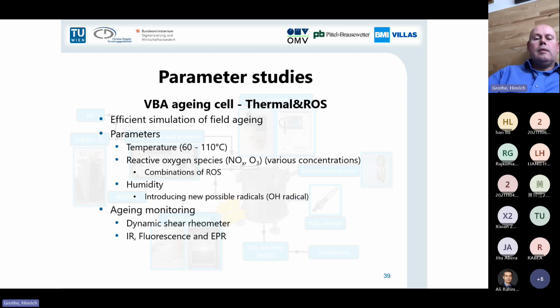So we were performing studies on the aging, and we were not using the pressure aging vessel test, but we were developing our own system. It's a Vienna binder aging. And the difference really is that here we can apply reactive oxygen species. That means we are using nitrogen oxide, we are using ozone, we can even apply light, form OH radicals if we want, and we can change temperature. We can control and analyze the gas phase very sufficiently and see concentrations. And we can change humidity. And finally, of course, we can bring that sample then to our different kinds of spectroscopy.